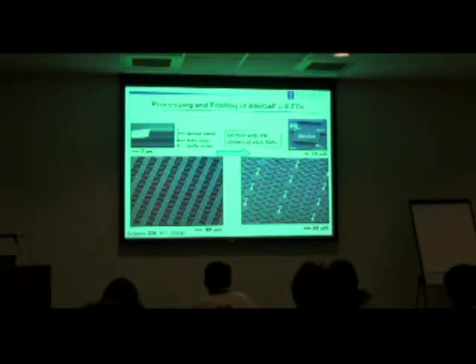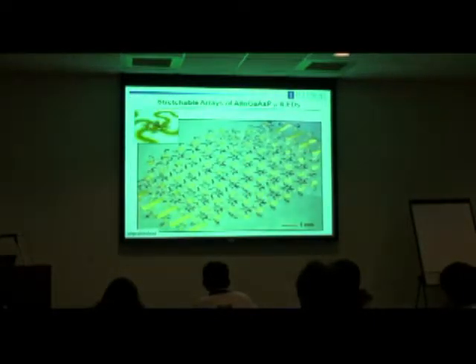So this is what the wafer looks like. And then we have soft rubber stamps that allow us to come in and pick off selected devices from the growth substrate and then deliver them down onto plastic or rubber for making functional systems. So here is an array of such ultra-thin LEDs interconnected using these non-coplanar serpentine ribbon cables I showed you before in the context of silicon electronics.